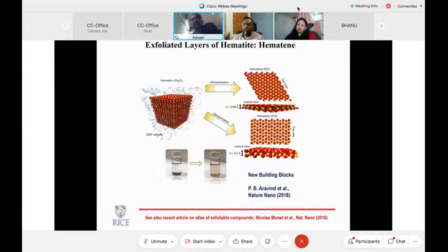So a tremendous amount of work has been done in exfoliating and optimizing the exfoliation technique of various layered systems. That's an art in itself. And this particular image I wanted to show because this is not a traditional layered system. It's iron ore, basically, alpha Fe2O3. One thing we showed a few years ago was that even these traditionally non-layered structures can be exfoliated along certain crystallographic directions if you have the right kind of energy. In fact, this article that I quote at the bottom, from Nicolas Mounet et al. in Nature Nano, gives you a map of pretty much all the possible materials that you can exfoliate, and along which crystallographic planes they will exfoliate with the minimum amount of force.